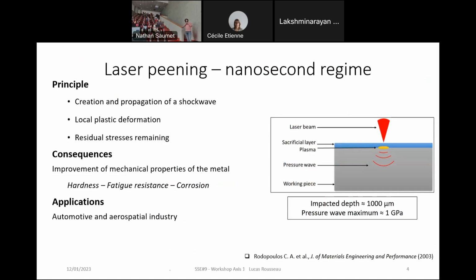So I will now speak about the physical principle behind laser pinning. First, the most well-known pinning, which is at nanosecond regime. The principle is to create and propagate a shock wave into the material. During this propagation, if the shock wave has high pressure, there is a local plastic deformation, and after the propagation of the shock wave, residual stresses remain, which will impact the mechanical properties of the metal, including its hardness, its fatigue resistance, or its resistance to corrosion too.